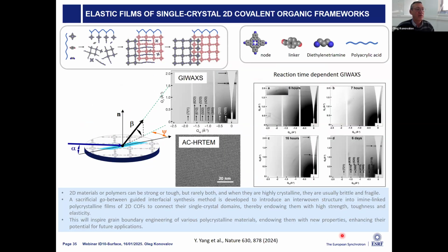So then another type of application is to show that we use some organic molecules to grow organic frameworks in 2 dimensions, and then afterwards even to grow a second layer and make a kind of weave between them and between patches, which makes these 2-dimensional crystal organic frameworks more stable, less brittle, and easier for application. Then at different times of this growth process, we can characterize the structures with GIWAXS.